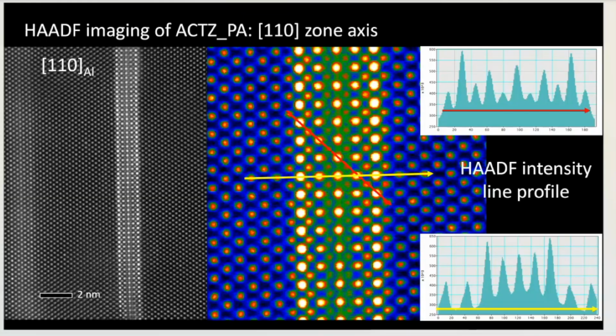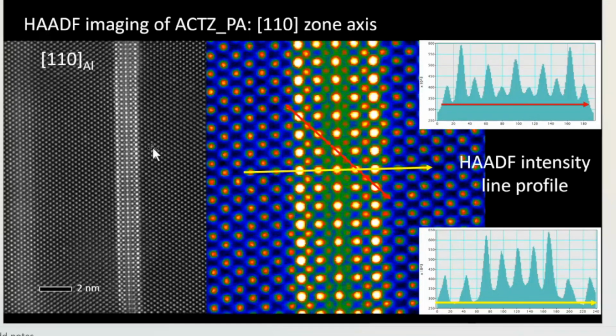So you can see a precipitate. This is a theta prime in HAADF mode, and you can see that there's a bright column at the interface. And this bright column, if you trace, you can see that there's a segregation because only the interface is brighter. Inside it is not so bright. And we assumed, we'll prove later, that these are actually the combined segregation of zirconium and tantalum. At this point, our microscope could not resolve the columns of zirconium and tantalum. So we must say that it is either a mix of zirconium and tantalum.